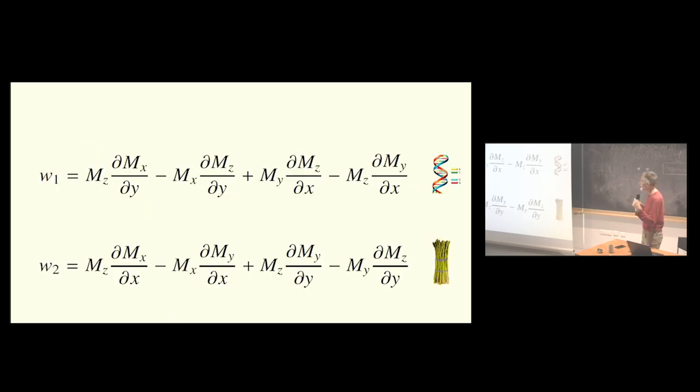What is interesting is that in uniaxial magnets, the symmetry of these terms is just given by these vectors or bidirectors. For example, the one which gives the Bloch skyrmion has the symmetry of a chiral bidirector, which is oriented along the z-axis. And the one which gives Néel skyrmions has the symmetry of polarization.